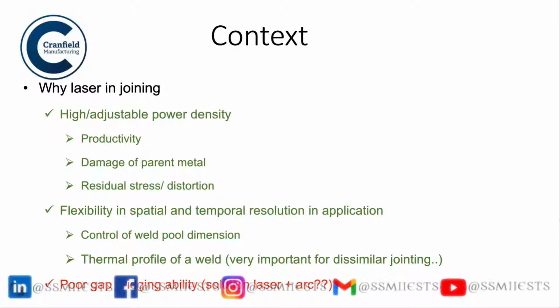However, laser has a disadvantage, that is poor gap bridgeability. This is a very important thing, because when you do a joint, often it happens that the joint is not perfectly aligned. So you need your power source, or the heat that you're applying, to have a gap bridging capability, and in that laser would not be very good. So a solution could be laser together with arc. That gives you the final solution on this.